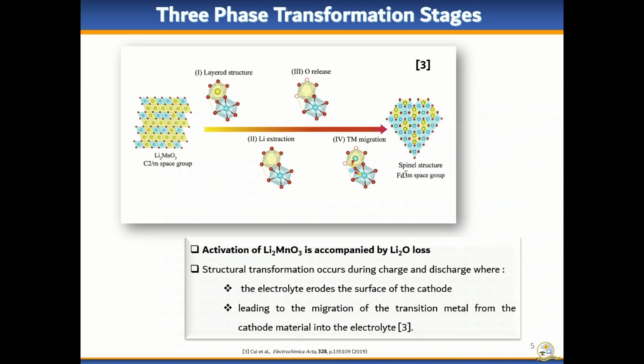So over here we demonstrate what happens during the phase transition. Basically, during the charging process, the lithium ion is removed from its original site and transferred through the electrolyte into the anode. And normally where there is a vacancy, the lithium that is transported leaves with the oxygen, it releases the oxygen, and this is something we do not desire, because after this we have vacancies. As you can see, these are vacancies formed when we remove the lithium. So what happens is that the manganese, this one in blue, now gets attracted to move to this position and forms a tetrahedral coordination instead of an octahedral coordination. And this actually blocks the pathways within the layered cathode materials and starts forming a spinel type structure.